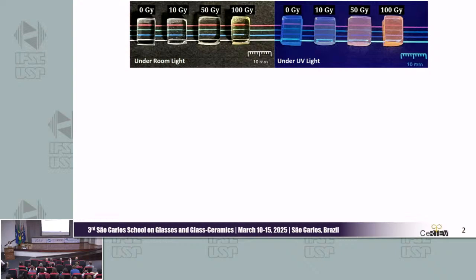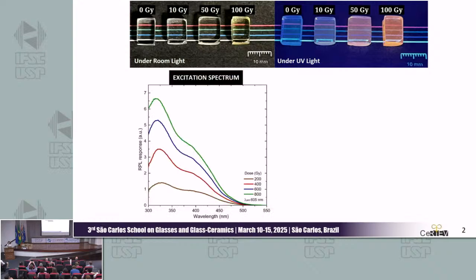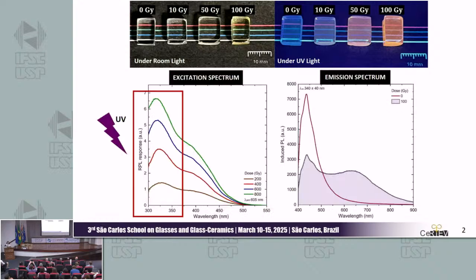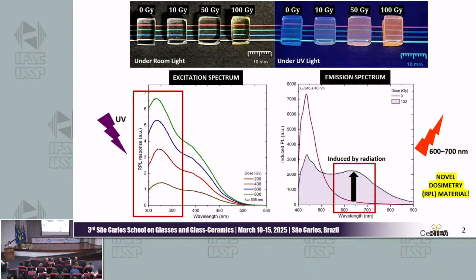This emission was further confirmed by the excitation and the emission spectrum. Because with excitation, the most intense was the UV region, and for the emission, we have, after radiation exposure, the orange emission. So this can suggest a novel RPL material for dosimeter applications.